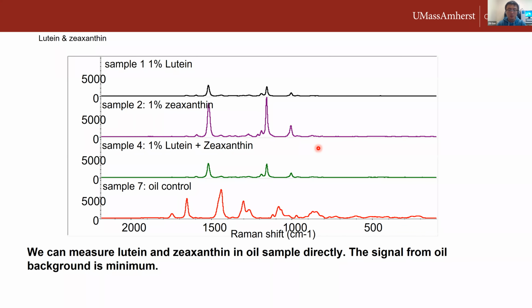In this experiment, since these two compounds are lipophilic, we dissolved them into the oil at 1%, individually and in the mixture. As you can see here is the background of the oil control. And when we made the samples dissolved in the oil, we found that these two compounds could be successfully identified through the oil solution. As you can see, these peaks are the signature peaks of these two compounds individually and in the combination.